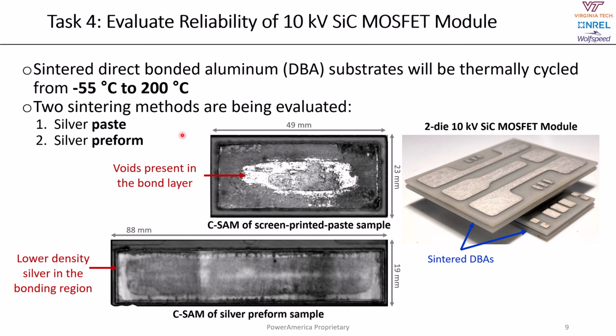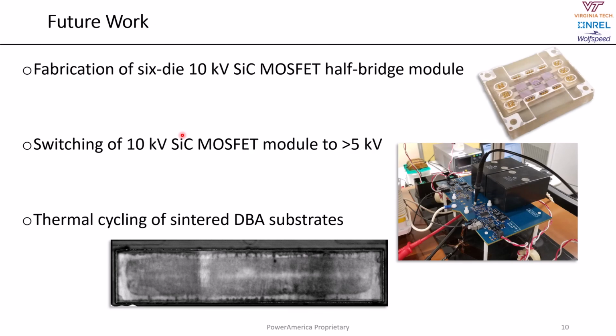We would now like to continue fabricating more samples, and we'll be evaluating their reliability using CSAM imaging under thermal cycling conditions from -55 to 200 degrees Celsius. So the future work is to fabricate more of these 10 kV half-bridge modules with 6 die total, 3 in parallel per switch position, to test the higher current capability of this type of package. We also want to switch this 6-die module beyond 5 kilovolt, and we want to evaluate the thermal cycling of these sintered DBA substrates, look at their failure, and also perform failure analysis.